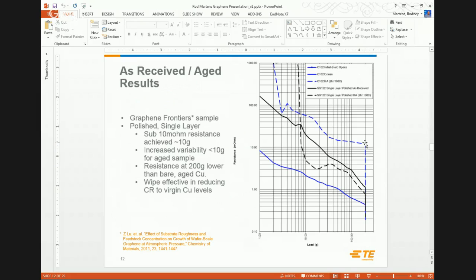What's also interesting to note here is you can see these lines all drop down at 200 grams to a fairly low value. This is where we introduced a little bit of wipe to all of these interfaces. What's interesting is once you add the wipe, which breaks through oxides, etc., they all come down to about the same value.